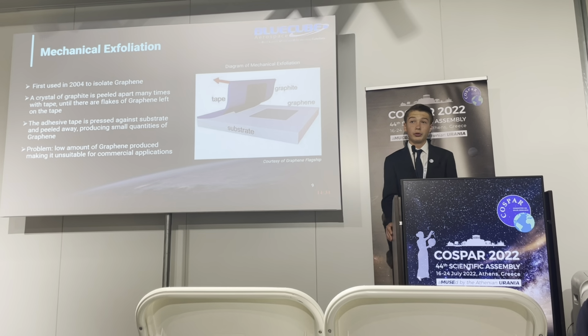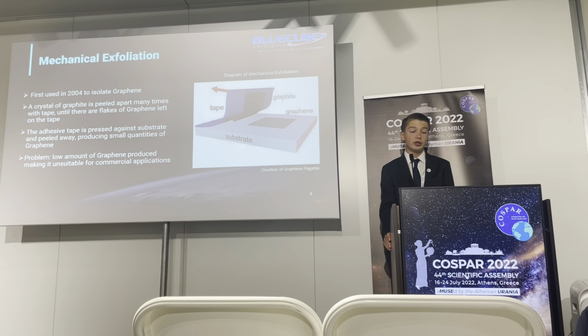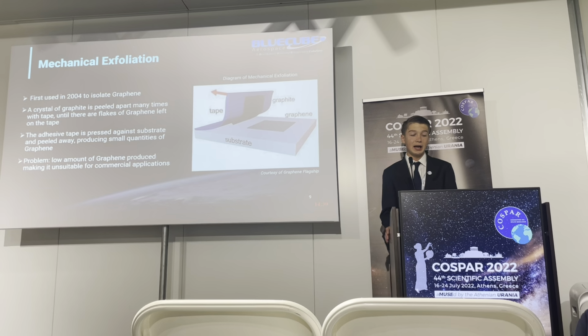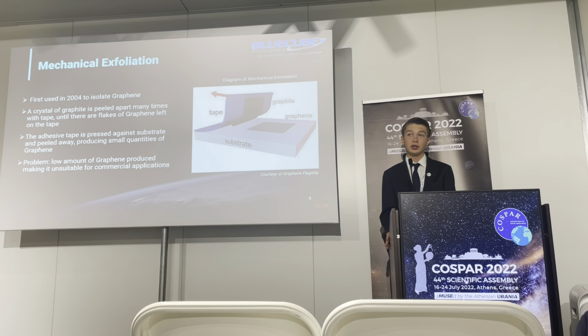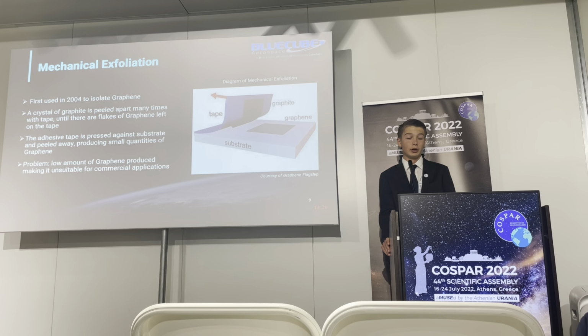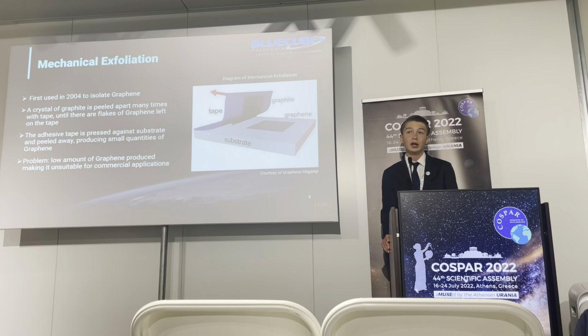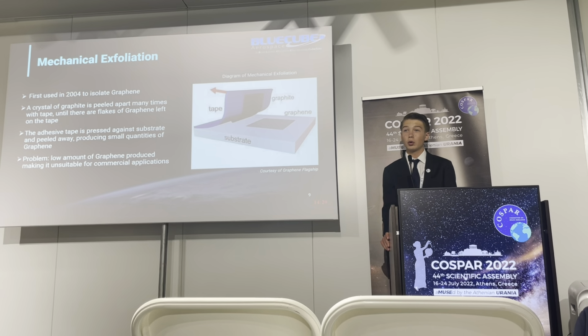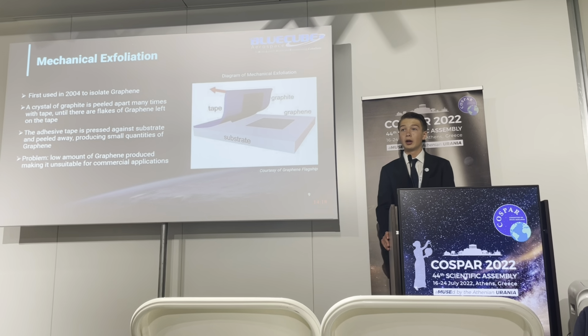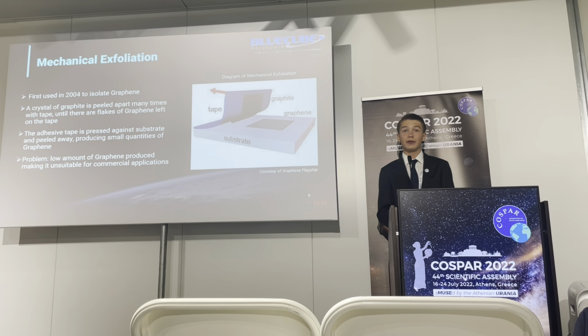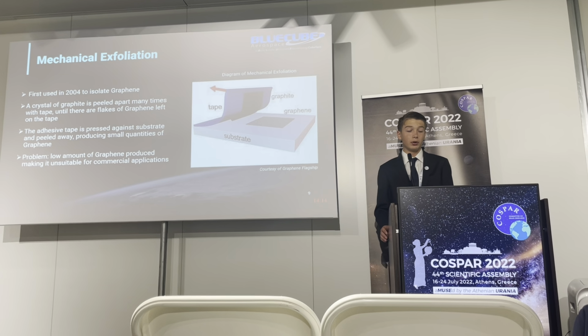So the way that this method works is a crystal of graphite is peeled apart many times with tape until there are flakes of graphene left adhered to the tape. This adhesive tape is then pressed against the substrate and peeled away, which produces small quantities of very high quality graphene. However, the small quantity of graphene produced renders it unsuitable for commercial applications.